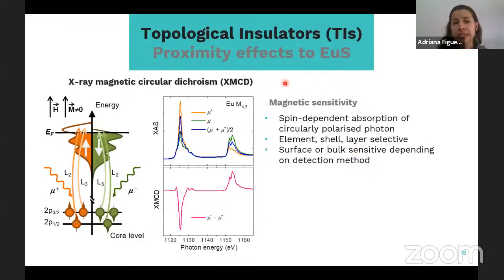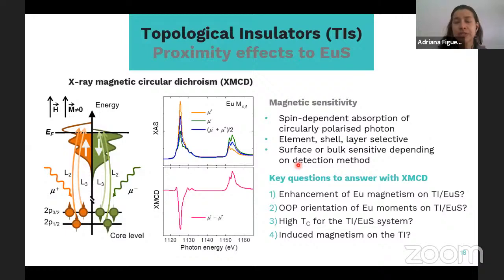Because by exploring these core level transitions, we can study what happens at the europium atoms or what happens at the TI atoms. So the key questions to answer with this element selective magnetometry are, first, is there an enhancement of the europium magnetism at these interfaces? What is the anisotropy of the magnetic moments at that interface, in particular the europium moments? Whether there is an increase of the Curie temperature, because it has been reported. And the most important part is whether there is induced magnetism in the TI, okay?